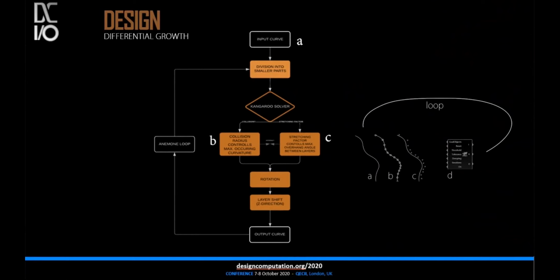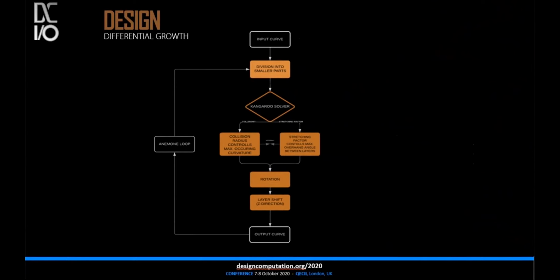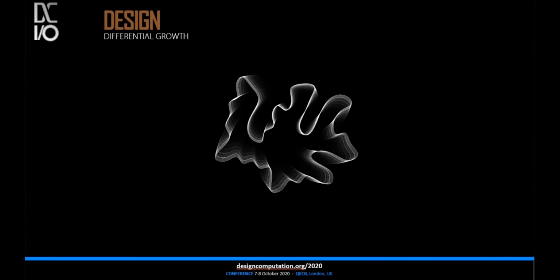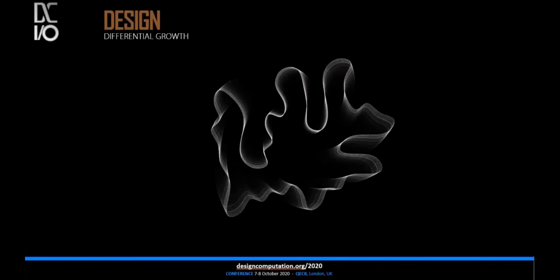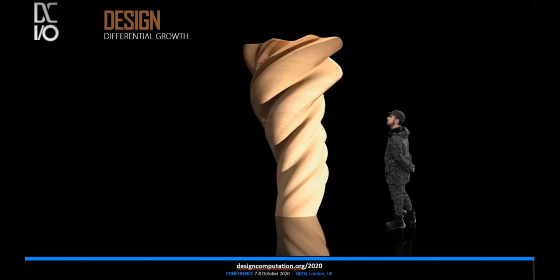These segments were given spring force characteristics to allow an overall growth of the input curve. Colliders in each endpoint of a segment prevent the curve of one iteration from crossing itself, to make sure that the radii of the curvature stay always within its printable maximum. In every iteration, the curve grows while traveling in the z direction within the layer height. An additional rotation parameter was applied to add a twisting behavior. This approach can take every curve as a basic input and creates growing designs through its maximum parameters as inputs.